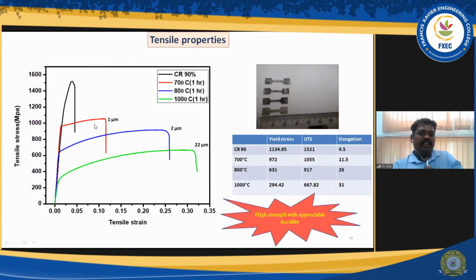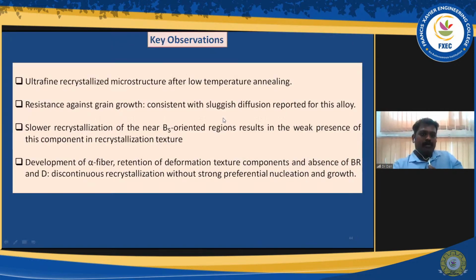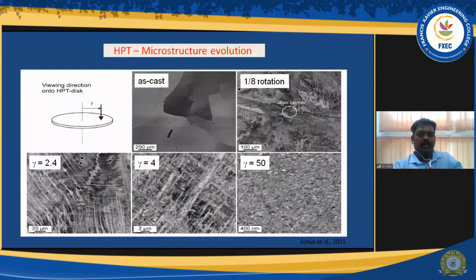Now I did some tensile tests. The ultra fine grain size gives very high strength, like 1500 megapascal, with appreciable ductility. With increasing grain size, I got an increase in ductility at the expense of strength, right? So in this study, I got an ultra fine grain size by grain refinement. Also, the grain growth is very slow in this material. The texture evolution is also very weak, a weak brass-type texture in this alloy. That is what I want to say about my work.